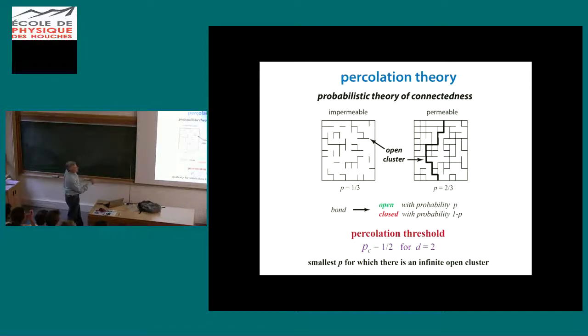And here we start, say, with a two-dimensional square lattice. A bond is open, the black ones, with probability P, closed with probability 1 minus P. This is about a third of them filled. This is an impermeable state. Here's a permeable state where there exists an infinite cluster in this infinite lattice. And then the smallest value of P, the probability for which you have the appearance of an infinite cluster, that is called the percolation threshold, which is exactly 50% in 2 dimensions.